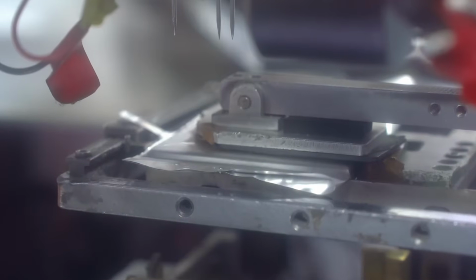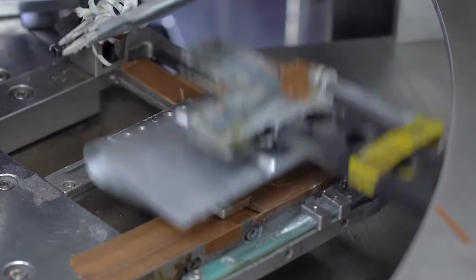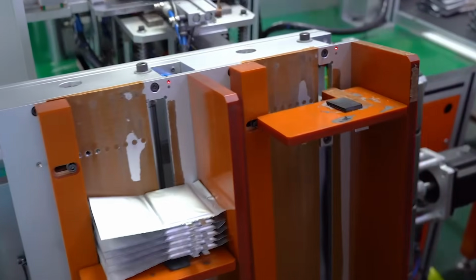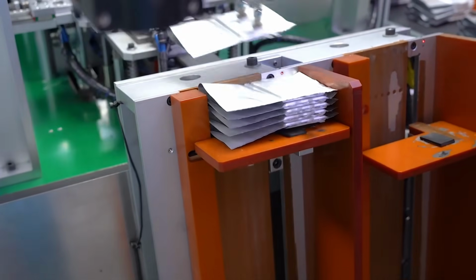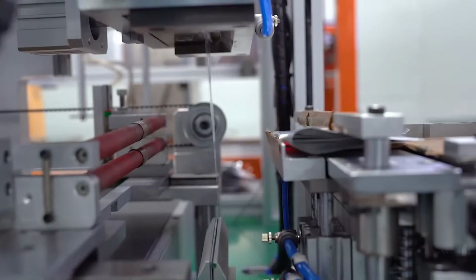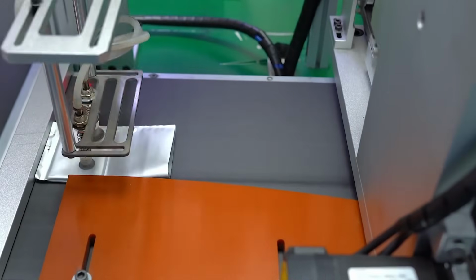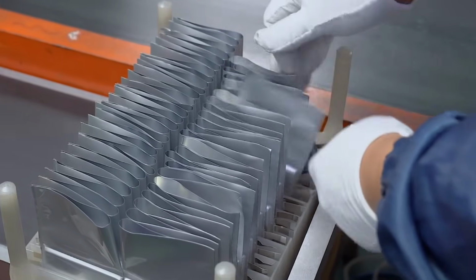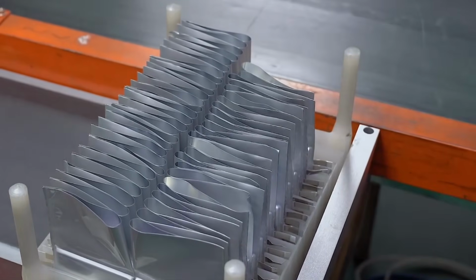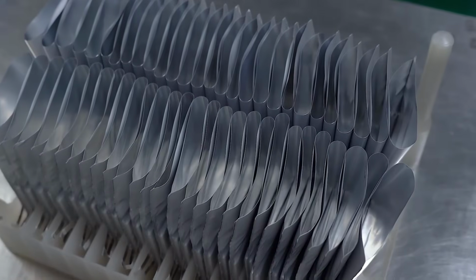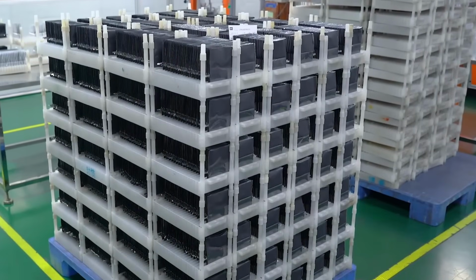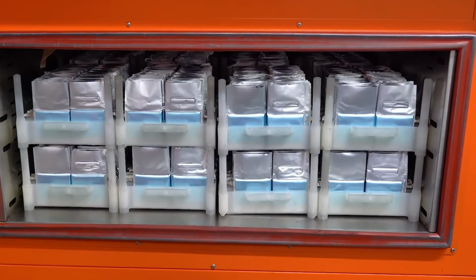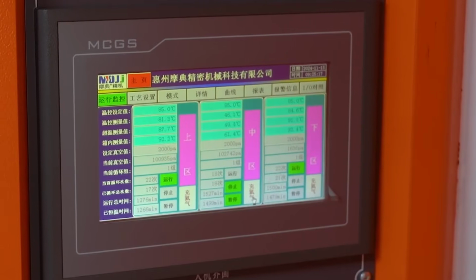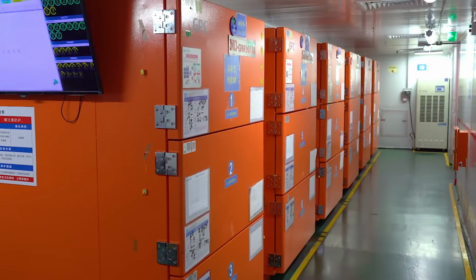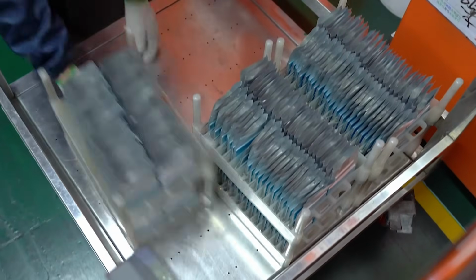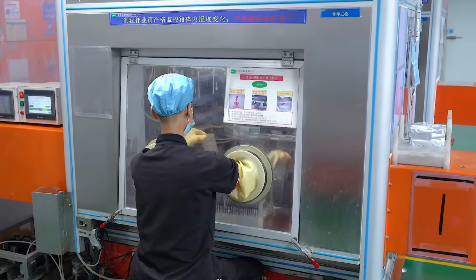Solid-state batteries replace the liquid electrolyte with a solid material, which promises higher energy density and better safety, but requires entirely new manufacturing processes that nobody has yet cracked at gigascale. Sodium-ion batteries swap lithium for sodium, which is almost absurdly abundant and cheap, at the cost of somewhat lower energy density that may not matter for stationary storage where weight is irrelevant. Silicon anodes pack more lithium ions per gram than the graphite anodes used today, which would meaningfully increase cell energy density, but silicon expands and contracts during charging in ways that crack the electrode over time. And solving that durability problem without adding cost is where a significant portion of battery research currently lives.